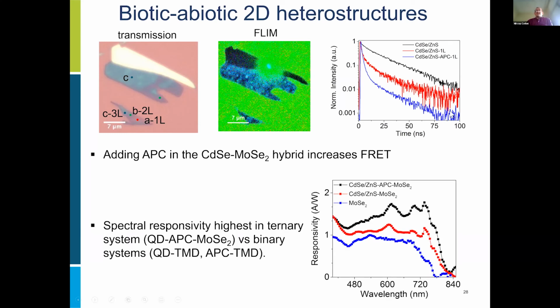Because when we make devices out of these components and measure the spectral responsivity, we get the highest values for this ternary system, quantum dots, protein, and the two-dimensional material, versus the bicomponents where we have quantum dots and 2D material, and protein and 2D material. So adding the biological motifs in this particular design actually increases the interaction and the sensitivity of the resulting device that we created.